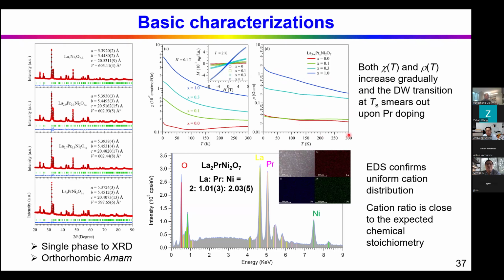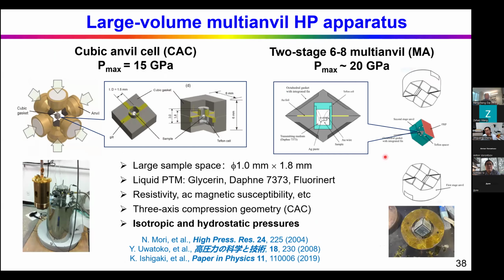But you also have more disorder, right? In the praseodymium doped sample, it's clearly more disorder. No, there's less disorder. You mean the intergrowth? Not intergrowth, but just the size difference between praseodymium and lanthanum, right? And you can scatter electrons, right? Yeah, but fortunately, the praseodymium goes to the lanthanum 2 site. Ah, okay. Yeah, it's between the bilayers.